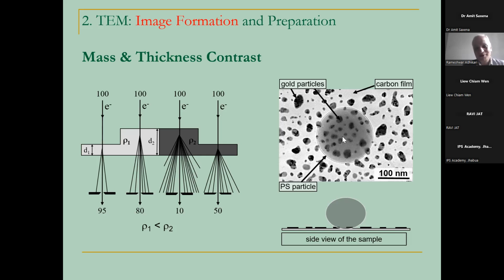So for example, just have a look at this electron micrograph. This is the transmission electron micrograph. The scale bar is also shown. The bright areas, for example this, are the areas where the amount of scattering is very low. And if we have here the particles which have higher densities, in this case the gold nanoparticles, inorganic particles, they scatter more electrons, and they become darker here.